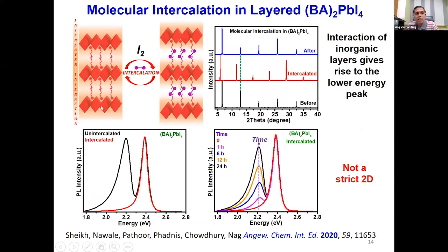So we have this layered perovskite structure, and to this we can intercalate various molecules, inorganic, organic. Here I'm taking the example of iodine intercalation. Before the intercalation, this was the XRD pattern, and after the intercalation you see that the interlayer distance increases, so the XRD pattern shifts towards lower 2 theta values. Interestingly, this iodine can also come out. So it's a reversible process. When iodine comes out, the XRD pattern comes back to the original position.